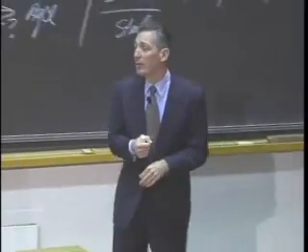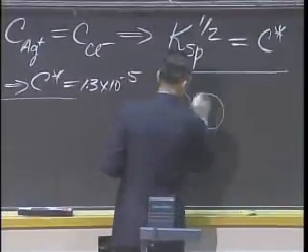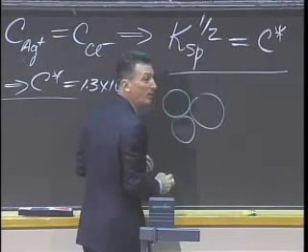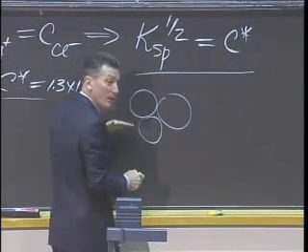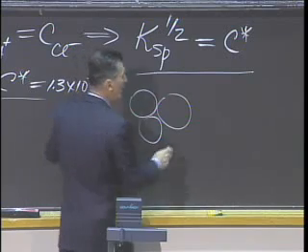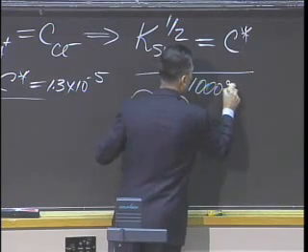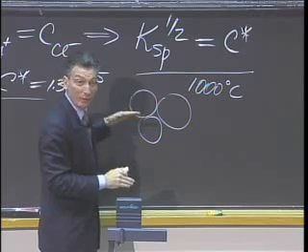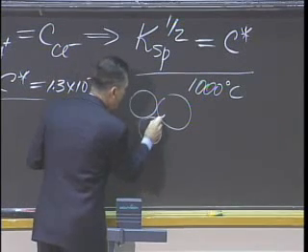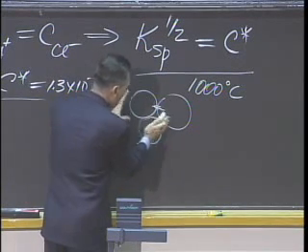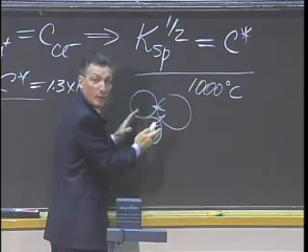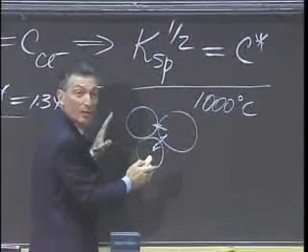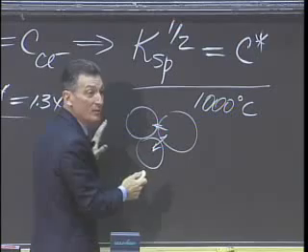So what do they do? They use solid-state diffusion, starting with particles of zirconia, fine particles, which are compressed, raised to elevated temperature on the order of about 1,000 degrees Celsius, and held there for several days. And during that time, diffusion takes place to reduce the void space, bringing this to near 100% density.